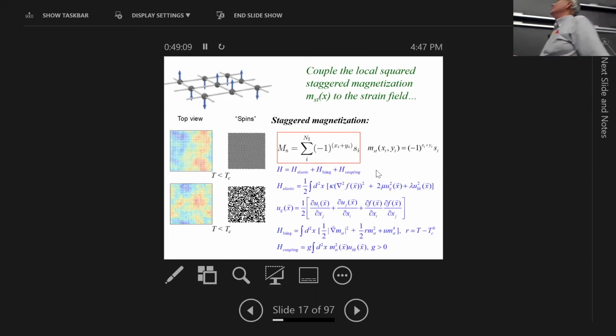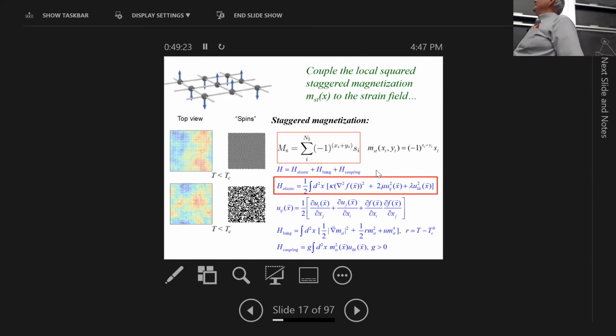Now, I apologize for this slightly busy slide, but it's things you've already seen, coupled together. So this is the flexural phonons, just what I was talking about earlier. That describes the flexural phonons. And this is this nonlinear strain matrix. This is what you might have encountered in a graduate stat mech course. This is a Landau theory for an Ising antiferromagnet with a staggered order parameter. This is the thing that changes sign at TC in 2 dimensions.